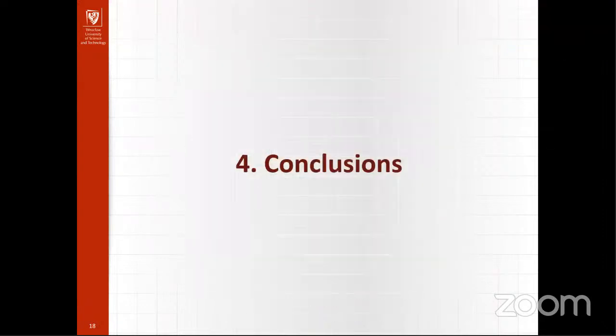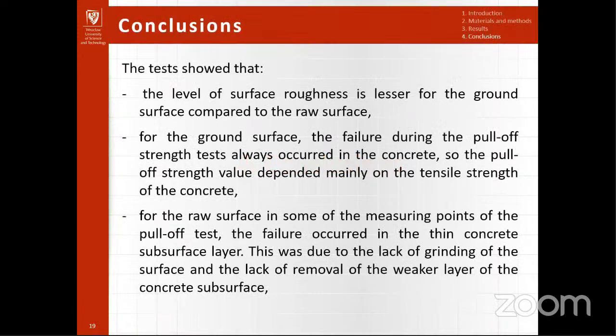Finishing with the conclusions. The tests showed that the level of surface roughness is lesser for the ground surface compared to the raw surface. For the ground surface, the failure during the pull-off strength test always occurred in the concrete, so the pull-off strength value depended mainly on the tensile strength of the concrete.